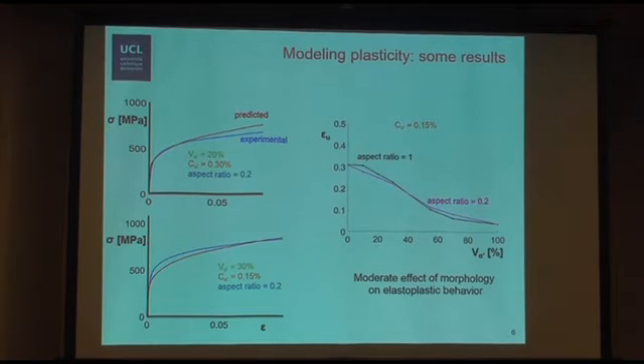This is another result of the study. It's the uniform deformation epsilon using the Considère criterion as a function of martensite volume fraction. For two aspect ratios, the black curve is for spheres, and the pinkish curve is for platelets. At low martensite volume fractions, we overestimate the uniform deformation, and again, it's because of the lack of a stage 4 that I'm integrating in my calculations now actually. Anyway, the trends are certainly correct. For example, that epsilon decreases with martensite volume fraction.